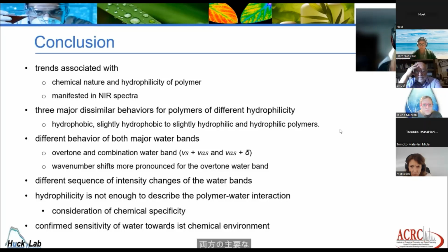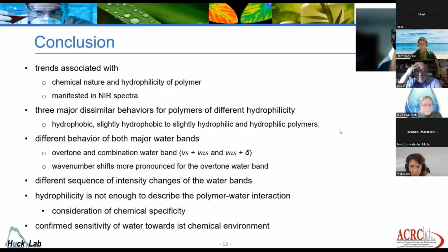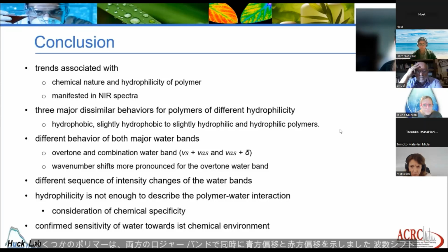Of particular interest is also the different behavior of both major water bands, the overtone and the combination water band, in the presence of diverse polymers. Some polymers even showed a simultaneous blue and red shift for both water bands. Wave number shifts are also much more pronounced for the overtone water band than they are for the combination band.